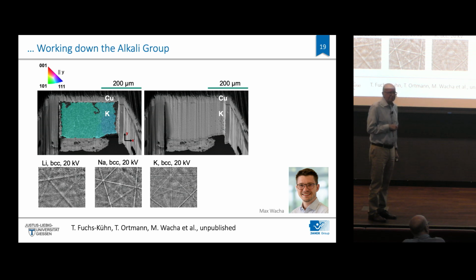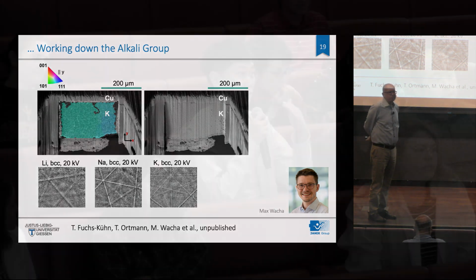I have a question regarding the grain size of this deposited lithium. As you deposit more lithium onto a current collector, the grains tend to grow larger. I think that's associated with larger grains absorbing smaller ones. If the grains are experiencing some reorientation or recombination, do you expect any local stress distribution change? And will this affect any electrochemical performance?